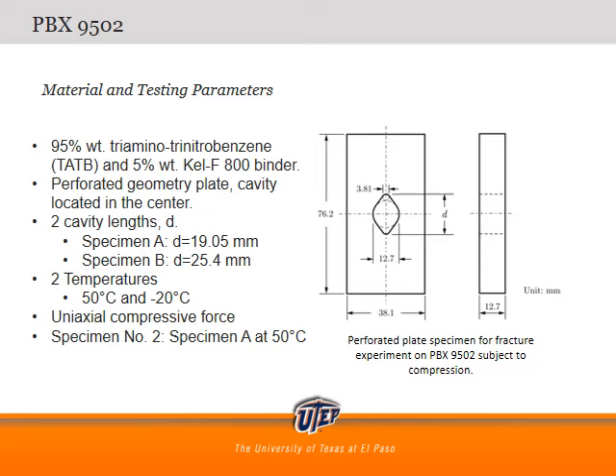2 cavity lengths denoted as D will be used in the experiment. Specimen A has a cavity length of 19.05 millimeters, and specimen B has a cavity length of 25.4 millimeters. 2 temperature ranges will be used, and they range from 50 degrees Celsius to negative 20 degrees Celsius. It is under a uniaxial compressive force, and for this experiment, specimen number 2, which is specimen A, at 50 degrees Celsius will be used because it proved most responsive to the testing.